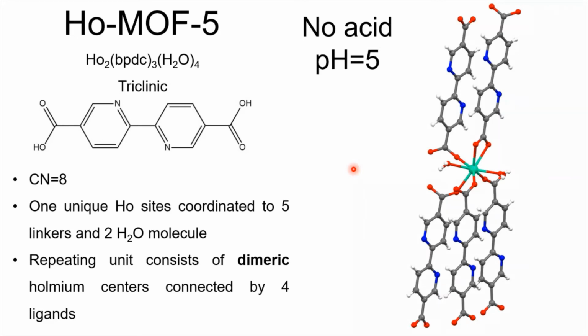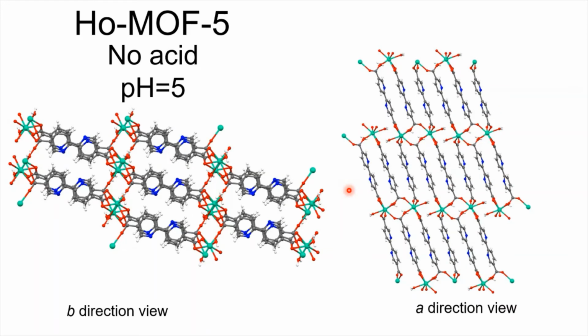And this is with no acid, so the pH is a little bit acidic due to the nature of holmium. We use holmium chloride and holmium nitrate as our precursors, so these will make the solution slightly acidic. And as you can see here, only water coordinates. But you can see again, we're talking about dimers. So dimers is a prevalent structure motif that we see here.